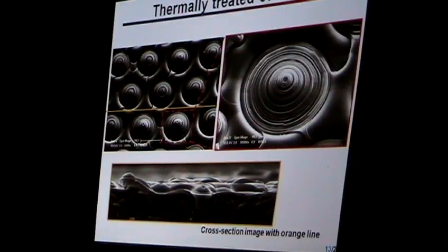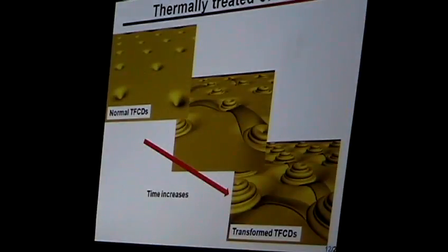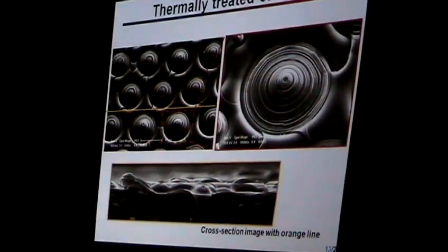Go back to the cartoon. So those donuts, so there's all that stuff, right? Yeah, these rings. This ring is made by smectic materials. I see. So there's nothing deposited. This just grows up out of the... No, this is sublimated and reoriented. I mean, the sublimated material comes out and is reoriented as it comes up to the surface. Exactly. I guess there is some competition between sublimation and reorientation at high temperature.